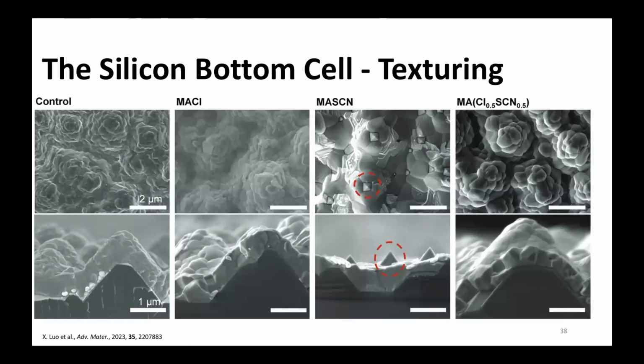And this represents the problems that they have with the big pyramid. So if you have the big structuring, it can happen that the pyramids of the silicon that you use stick out of the material. So they don't function. They use special mixtures of salts to get the best deposition with spin coating. This is another approach next to this nanostructuring.